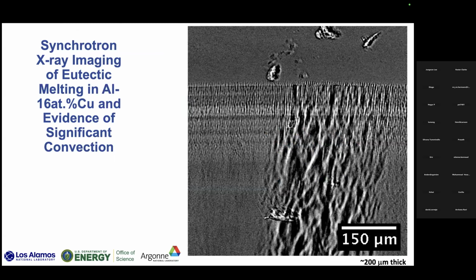I'm going to show a movie of synchrotron X-ray imaging of a near eutectic aluminum copper alloy. Here we're doing controlled directional solidification and melting. For context, this is a 200 micron thick film, which is on the order of the diameter of a human hair, so this is a very thin film sample. Here we've stopped a planar solid liquid interface in the field of view for the imaging. In the lower half, you see the solidified two-phase eutectic microstructure that appears lamellar in nature. The bright regions are the aluminum-rich phase, and the dark regions correspond to the Al2Cu phase. And then above, we have the alloy melt.